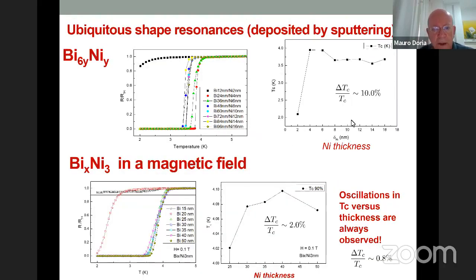Okay, we also looked at another system that is a little bit more complicated. We have deposition of a growing layer quantity of bismuth and a growing quantity of nickel. And if the nickel is sufficient, from 4 nanometers on, we have some oscillations on TC. So this is from original nickel thickness 4 up to 16. We begin to observe some oscillations. Here the TC, here are the oscillations again.